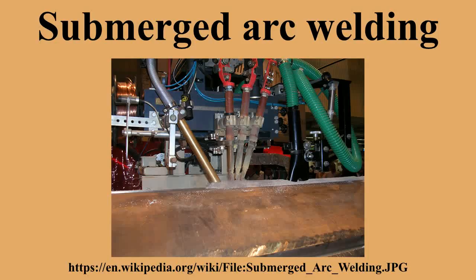Electrodes are available to weld mild steels, high-carbon steels, low and special alloy steels, stainless steel and some of the non-ferrous of copper and nickel. Electrodes are generally copper-coated to prevent rusting and to increase their electrical conductivity. Electrodes are available in straight lengths and coils. Their diameters may be 1.6, 2.0, 2.4, 3.2, 4.0, 4.8, and 6.4 mm. The approximate values of currents to weld with 1.6, 3.2, and 6.4 mm diameter electrodes are 150 to 350, 250 to 800 and 650 to 1350 amps respectively.